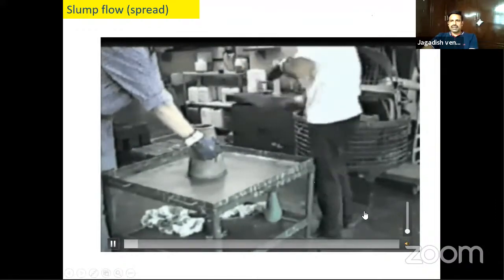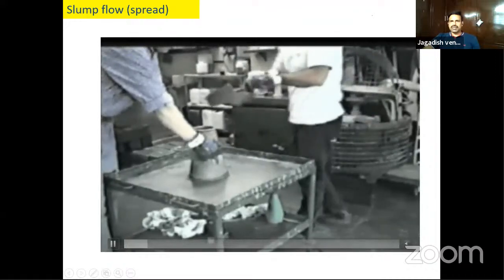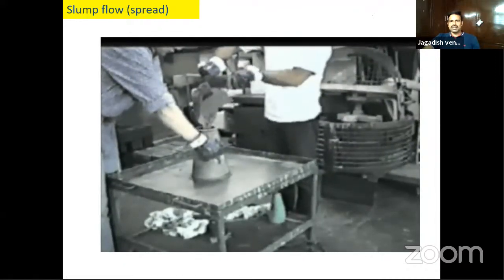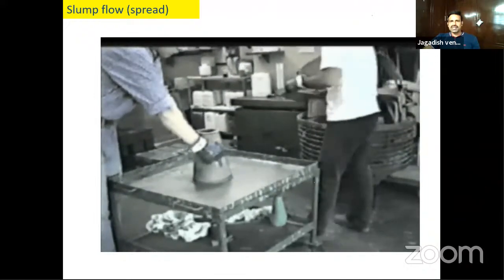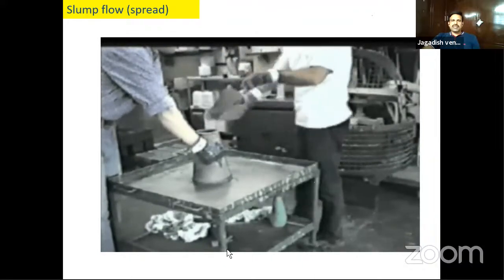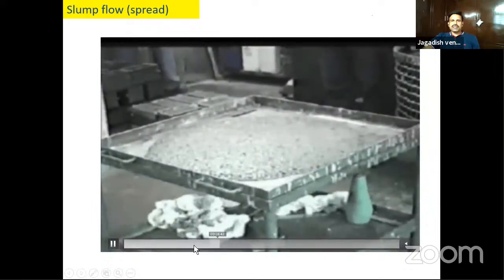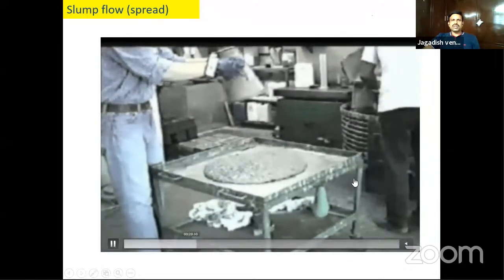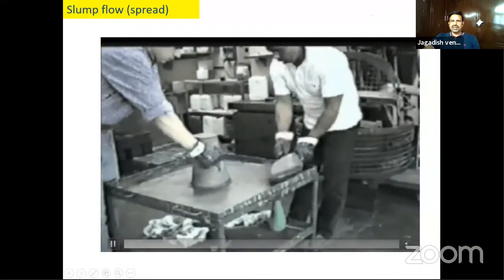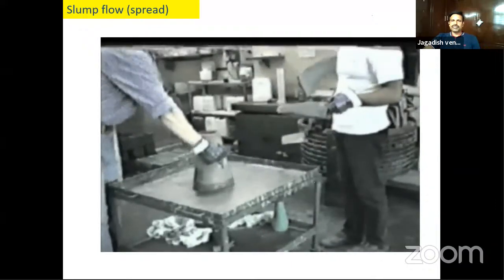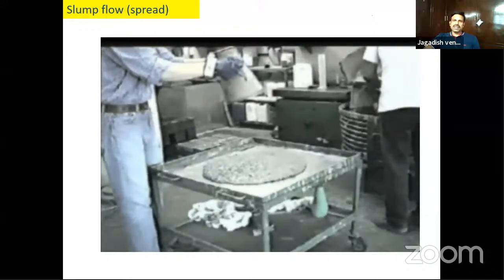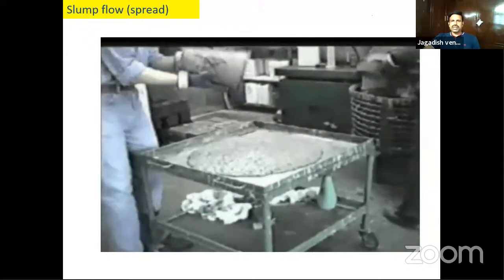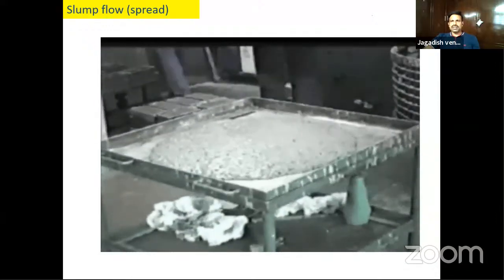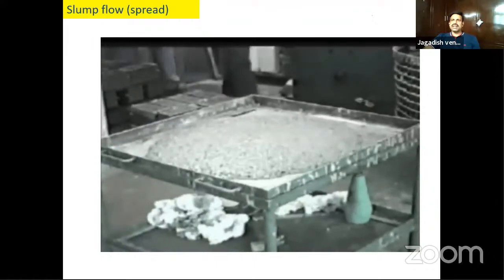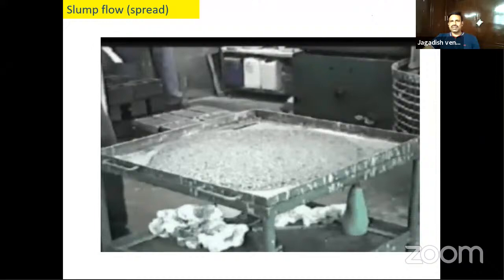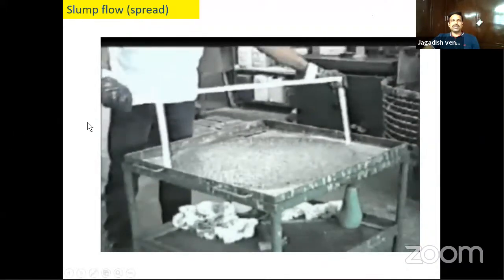You should not place the concrete and tamp it like normal concrete. You just have to pour the concrete once you mix it, and after pouring, you just have to lift the slump cone. This is how it spreads. You can measure the T50 centimeter slump flow, and the total horizontal spread the concrete has taken. And you can also observe whether there is any segregation or bleeding in the mix you have taken. This is how you measure the slump flow.